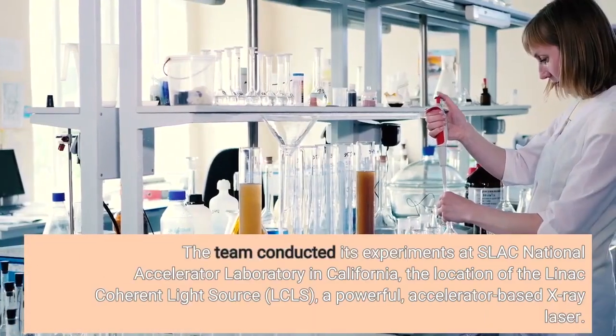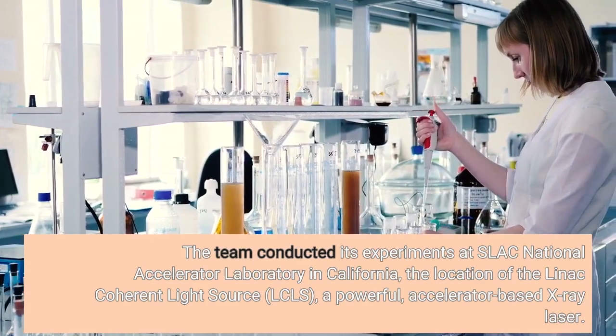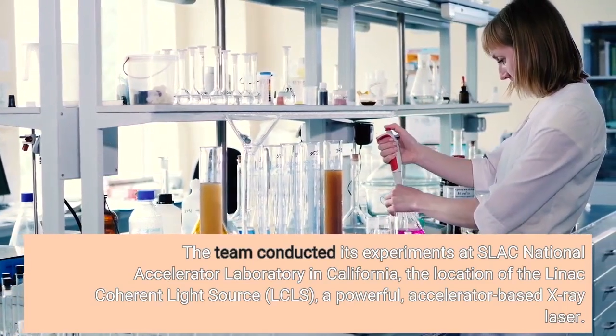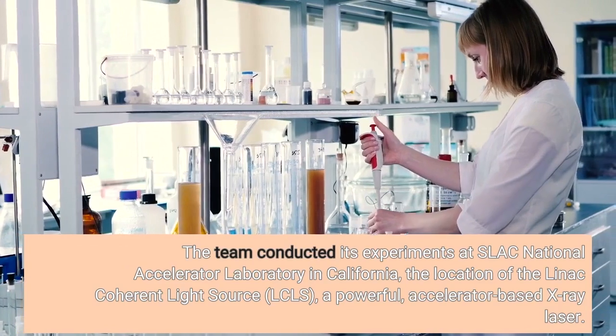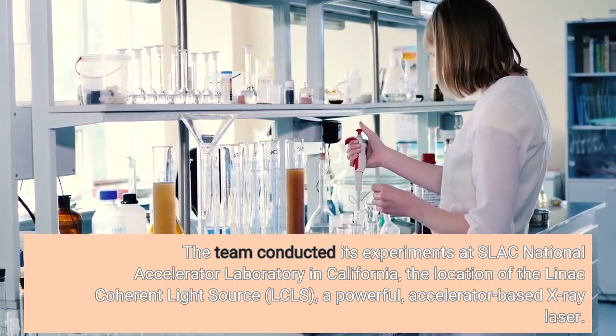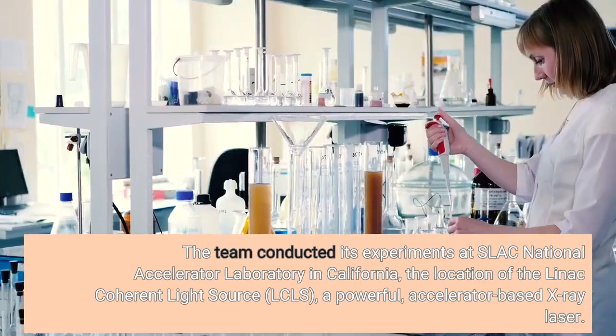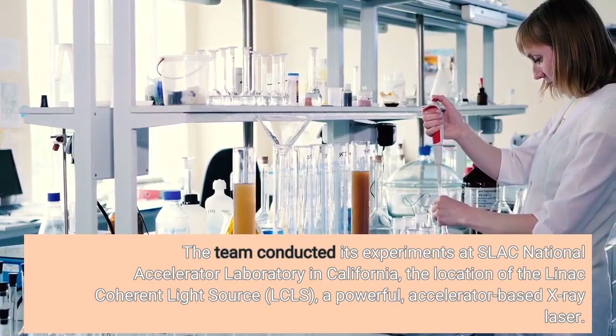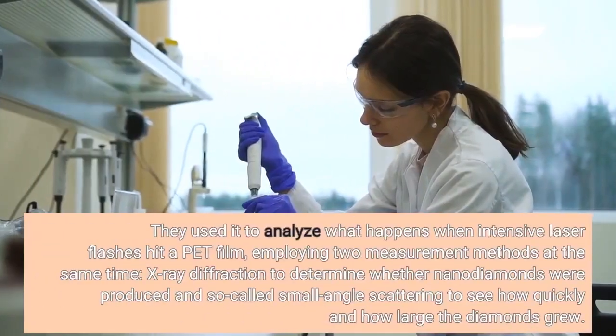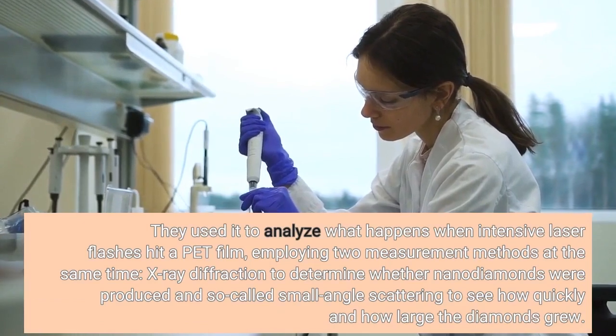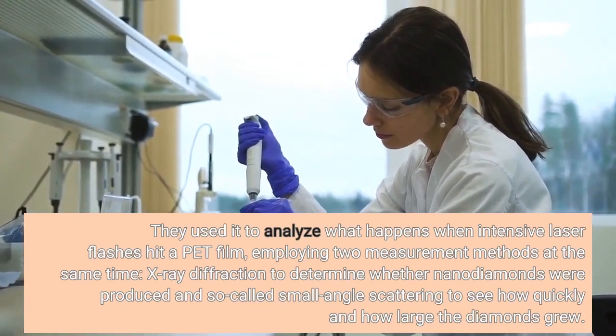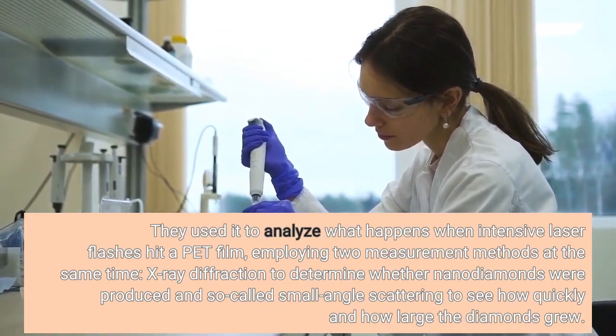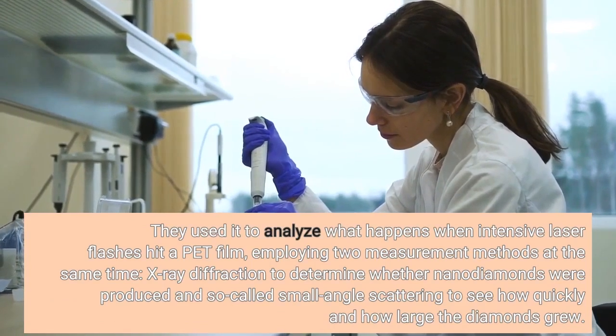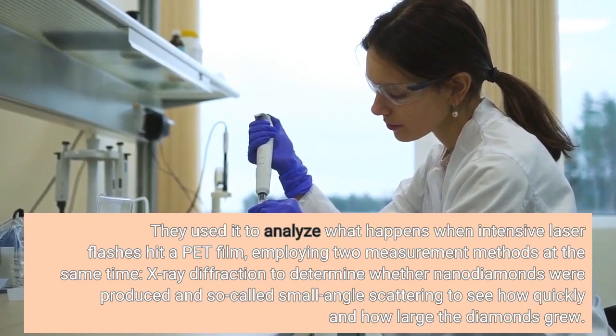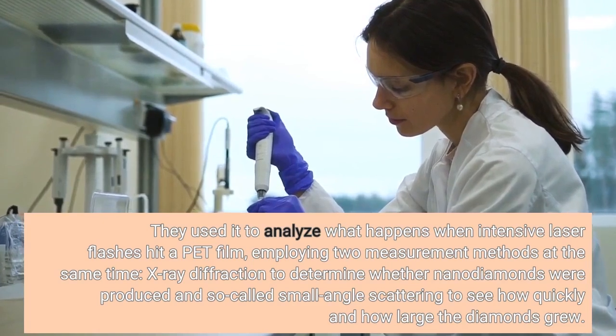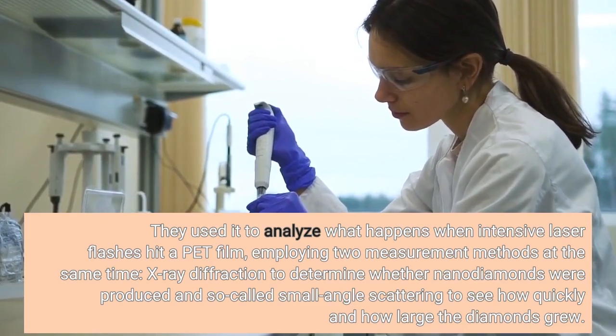The team conducted its experiments at SLAC National Accelerator Laboratory in California, the location of the LINAC Coherent Light Source, LCLS, a powerful, accelerator-based X-ray laser. They used it to analyze what happens when intensive laser flashes hit a PET film, employing two measurement methods at the same time: X-ray diffraction to determine whether nanodiamonds were produced and so-called small-angle scattering to see how quickly and how large the diamonds grew.